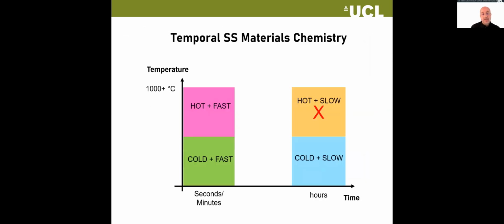And what I've tried to do is summarize, if we think about time and temperature, we're doing solid state reactions. I'm going to put them into 4 categories. So at the top end, at the hottest end, this is temperature and this is time. So in the case of the lanthanum nickelates, it took 12 hours. You had no choice, or 6 hours, depending on the type of lanthanum nickelate, because of the structural complexity and the fact that these precursors were reacting, but then also rearranging to form these structures.